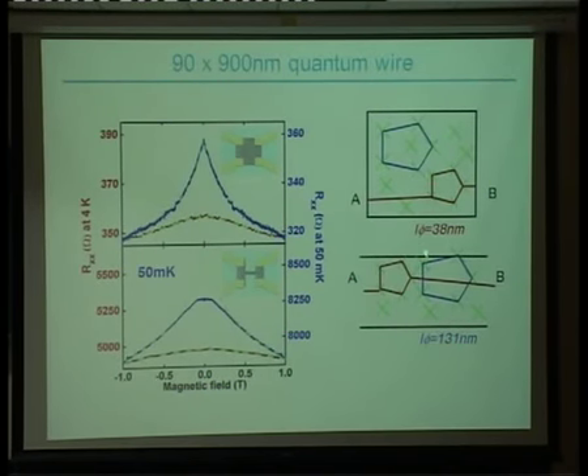But in these wire structures, which are only 90 nanometers wide, they can't form these phase coherent loops. So you get this saturation of the resistivity at a lower field value. And if you look at the magnetic field value at which these 2 deviate, you can work out what the magnetic length is and then the width of the wire, and it comes out to be 93 nanometers.